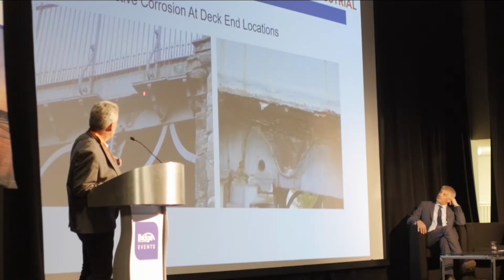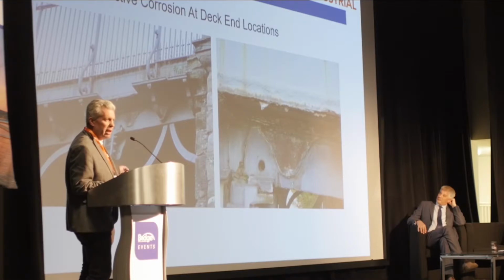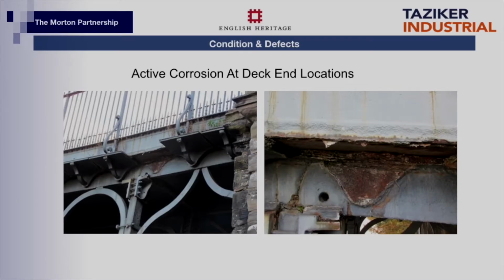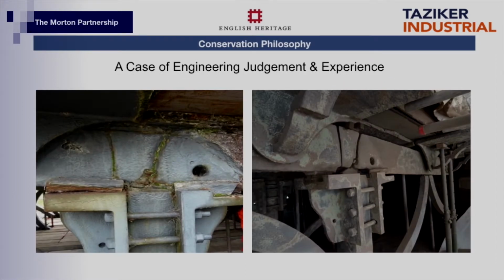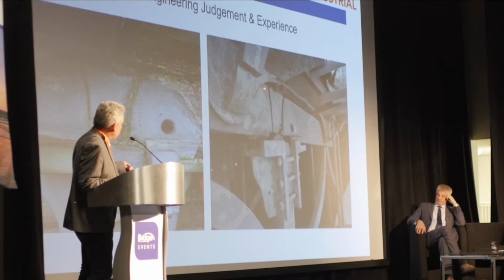One particular concern was the deck end plates. So these are continuous plates which run across the bridge, and they have these lobes at the bottom. But as soon as you get any corrosion build-up at the back of that lobe, basically it jacks the lobe off. So we've had several which had fallen, and others which were actually found to be loose once we got the scaffold up. And again, an example of the types of fractures we were finding in the cast iron. And here's an early repair.